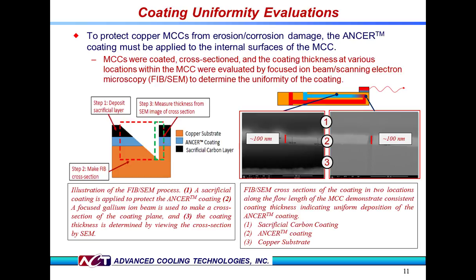Another good question that has been asked is how can you confirm that the coating is present and its thickness adequate over the MCC internal structure? The measurement is not trivial because the coating is very thin, around 100 nanometers or so, and somewhat transparent. To provide a discrete spot measurement, ACT, with its partners at Penn State, has developed a focused ion beam scanning electron microscopy technique, FIB-SEM for short.